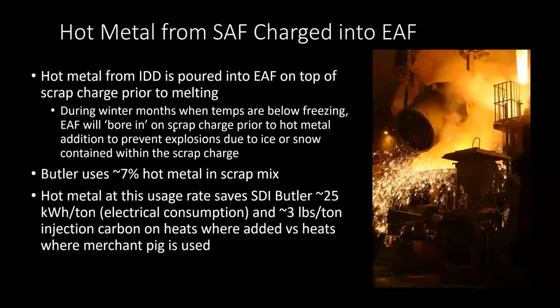Once it's below freezing, we pour our hot metal in on top of scrap that we already arced in on. But in the summer months, we pour our hot metal directly on our scrap without arcing on it. We use about 7% hot metal, and our hot metal on heats where we do use it saves us about 25 kilowatt hours per ton, and we use about 3 lbs less per ton of injection carbon.